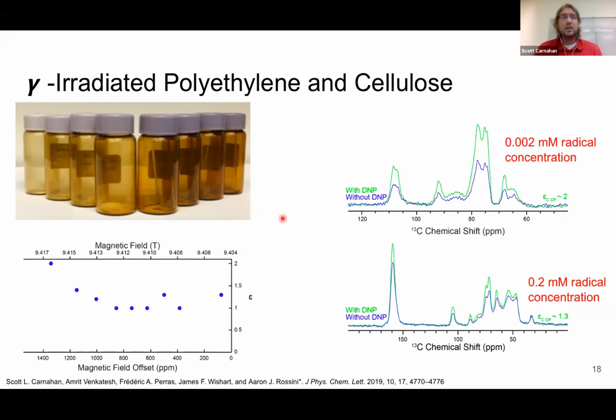In addition, we did gamma radiation of cellulose. And you can see we had a very low radical concentration in cellulose. Even though I only had a partial field sweep profile, we were able to hit a position where we could get at least an enhancement of 2. So there's still more that can be done here, trying to increase radical concentration or having a more thorough field sweep. We might be able to drastically increase this for some other samples too. The field sweep is the time-consuming part right now, because we just have a standard Bruker NMR magnet that I'm changing the field on, so it's a little slow.